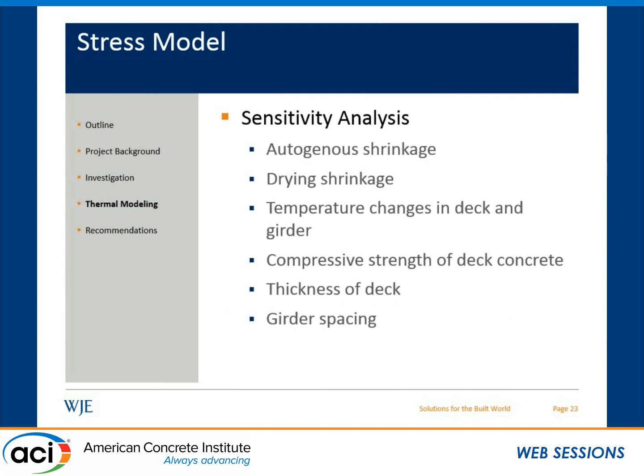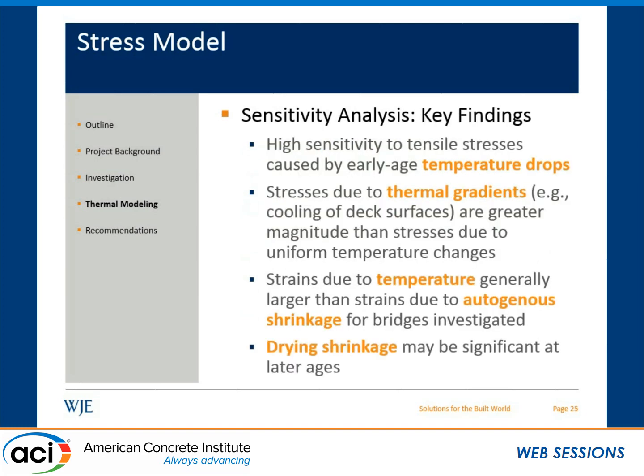And again, because we had to make a lot of assumptions in this model, we focused primarily on a sensitivity analysis. We wanted to understand what factors could contribute the most to the cracking potential at these ages. So we looked at a number of factors: autogenous and drying shrinkage. We looked at temperature changes in the deck and the girder, and we looked at both uniform and linear temperature changes there. And we also looked at compressive strength of the deck concrete, the thickness of the deck, and the girder spacing. I'm going to focus primarily on the first three of these, the shrinkage and temperature changes, just because they are the more important factors here.